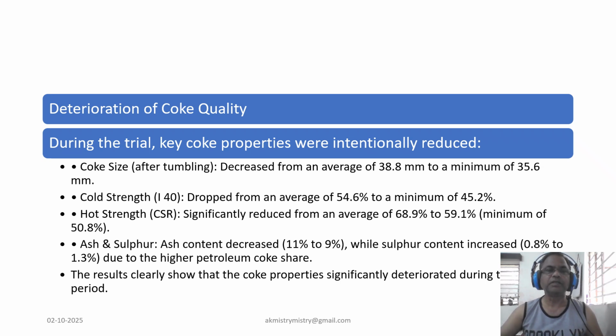The change in the coal blend had a clear and significant effect on the coke's properties. As you can see, the average coke size after tumbling decreased, and the coke strength measured as I40 dropped from a respective average of 54.6 down to a minimum of 45.2. Perhaps most critically, the hot strength or CSR value plummeted from an average of 68.9% to just 59.1%, hitting a low of 50.8%. This value is vital for the coke performance in the lower high temperature part of the furnace. Interestingly, while the ash content went down, the sulfur content increased due to petroleum coke. The data is unequivocal. The coke quality was substantially degraded during the trial period.